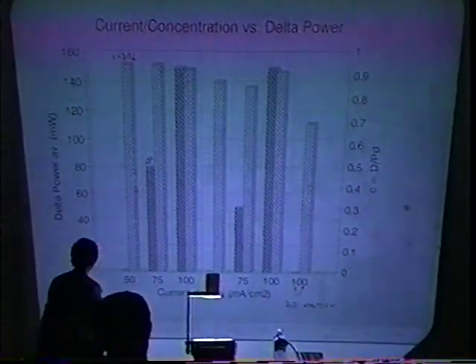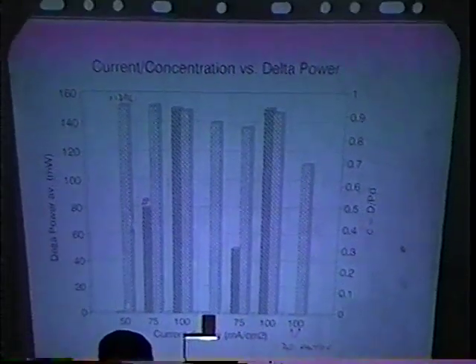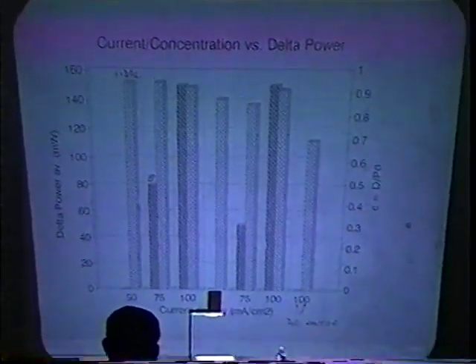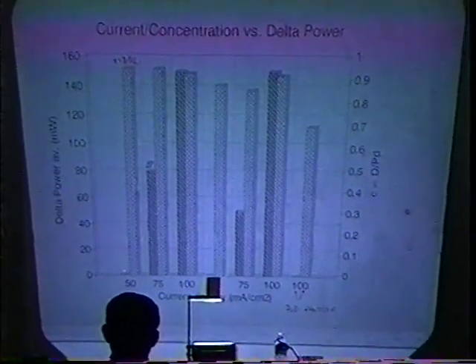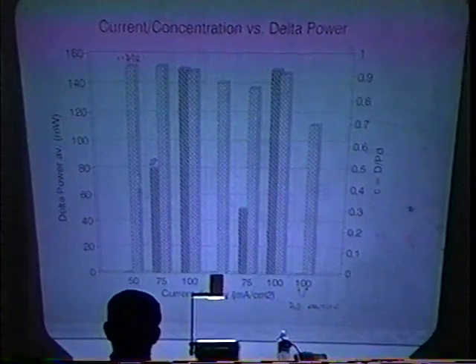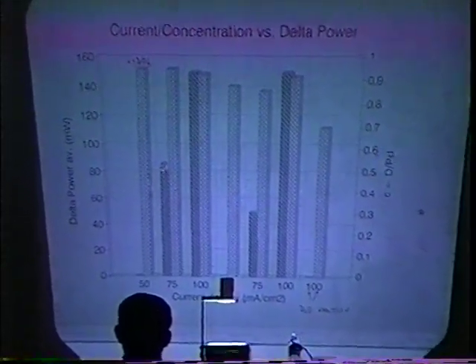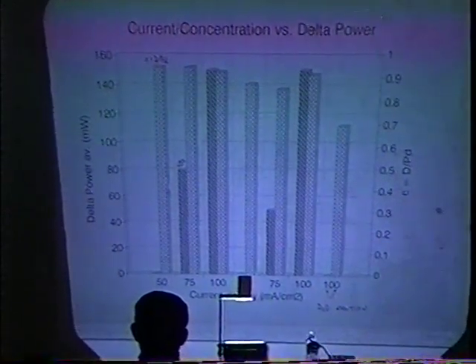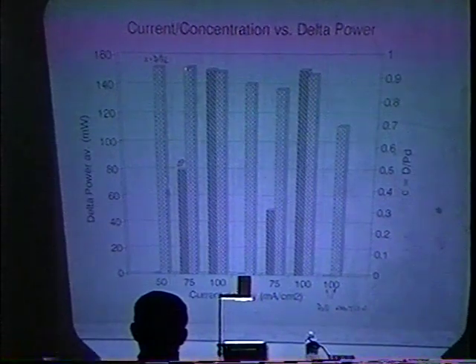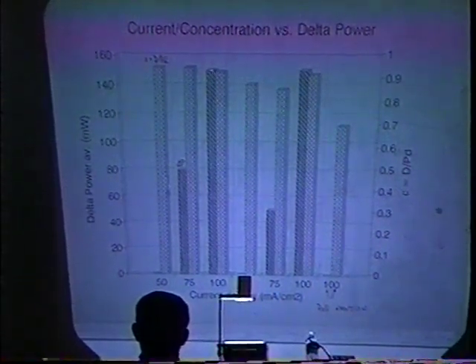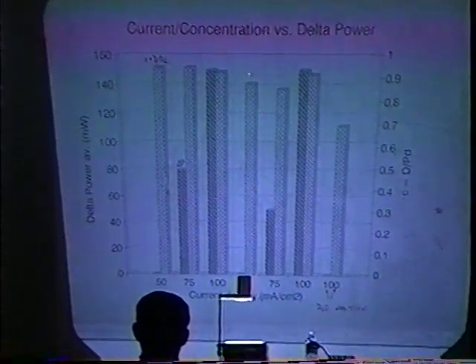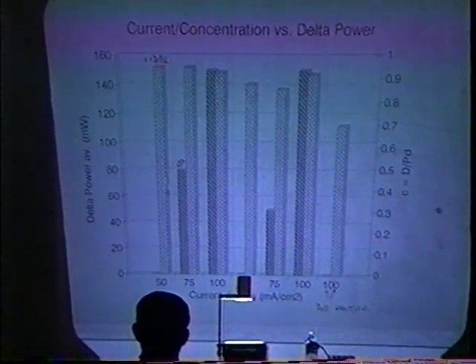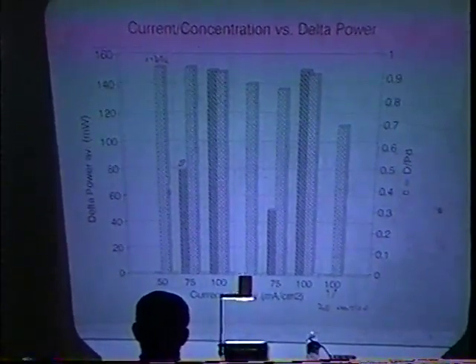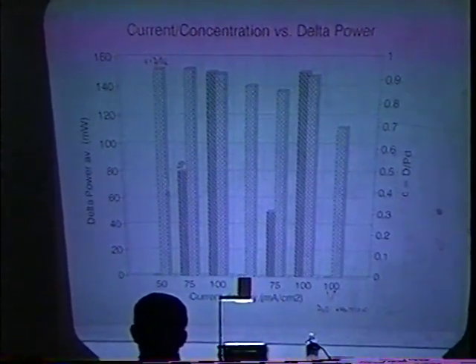Then, at the end, we decided, just a little bit more than 1 month ago, to start again with calorimetry. And these are the results. So, with low currents, we obtained a very high loading ratio with deuterium, and no excess heat. By increasing the current, we obtain the excess heat well above the sensitivity of our system for 2 watt of input, as in this case, with a very high loading ratio. By increasing the currents, the excess heat increases again. By reducing the electric power applied to the cell, the excess heat disappears, and appears again when we increase the current again.